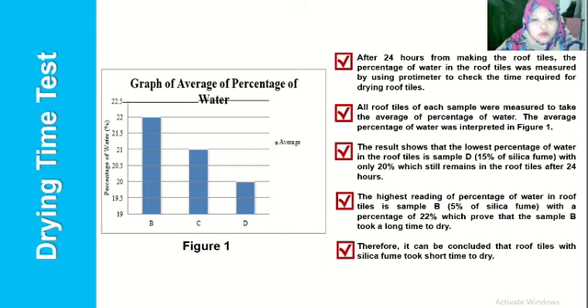Let's proceed to the second test, which is the drying time test. After 24 hours from making the roof tiles, the percentage of water in the roof tiles was measured using a protimeter to check the time required for drying. All 3 roof tiles of each sample were measured to take the average percentage of water. The average percentage of water is shown in figure 1 here.